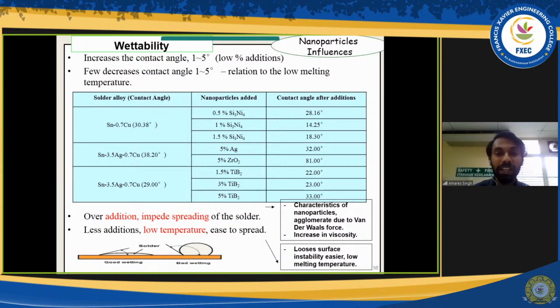So here it's important to keep the weight percentage or the addition as low as we can, because even a small amount of nanoparticle additions can actually increase the other properties such as mechanical. We don't need a lot. Whereas it's different when you're trying to add in a bulk element. If you add in a small amount of bulk element, it does not give any significant improvement. So let's go to the next part.